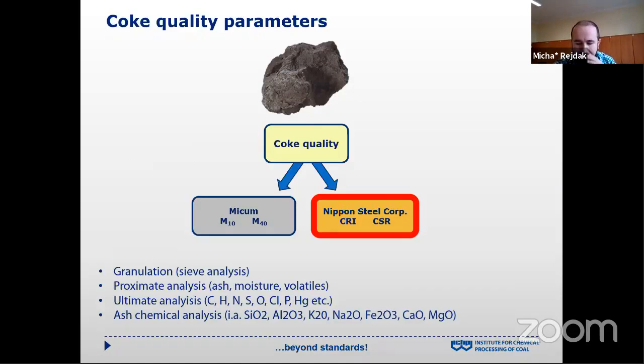Currently, the basic parameters in assessing the quality of coke are Micum indices and Nippon Steel Corporation indices, such as coke reactivity index CRI and coke strength after reaction CSR. Moreover, significant parameters for the processes of using coke are the granulation, sieve analysis, proximate analysis like ash, moisture, and volatiles, ultimate analysis: carbon, hydrogen, nitrogen, sulfur, oxygen, chlorine, phosphorus, or mercury content, and as mentioned before, ash chemical analysis, because some of the ash oxides or some of the minerals have catalytic action on the reaction of gasification of coke by carbon dioxide.